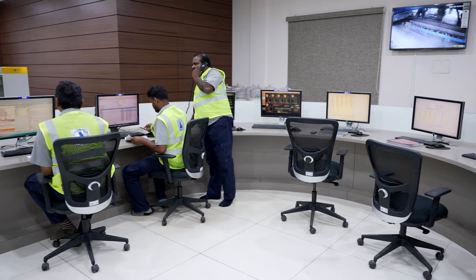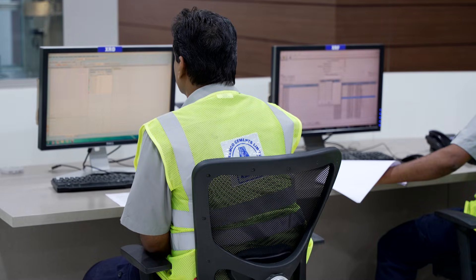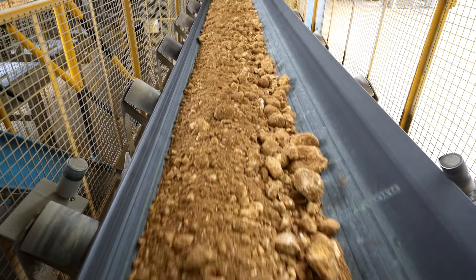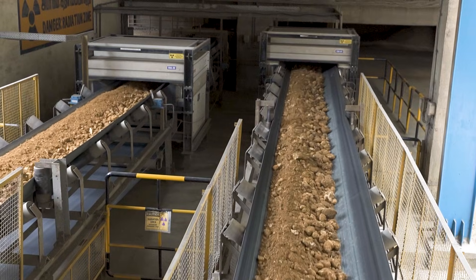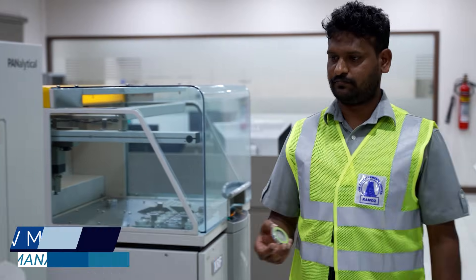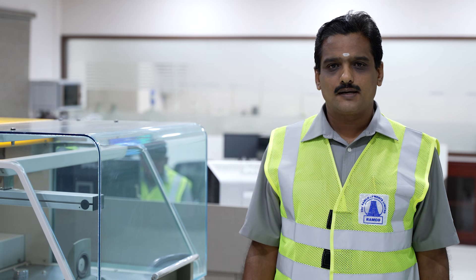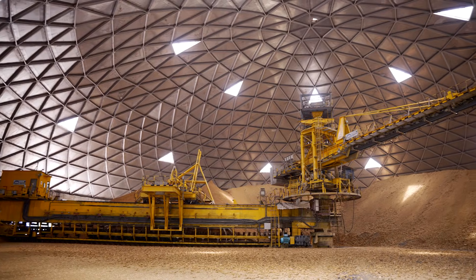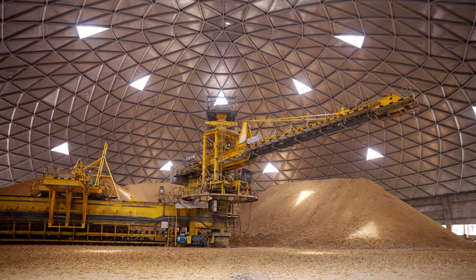The team at Ariyelur takes utmost care at each and every stage of quality in the cement manufacturing process. We have a cross-belt analyzer which gives minute-wise results at the rate of 1000 MT per hour, helping us to homogenize different sources of limestone. We also have modern XRF and XRD equipment which analyzes raw material, additives, kiln feed and cement. The stacker and reclaimer system helps to maintain homogenized limestone quality toward the pile.